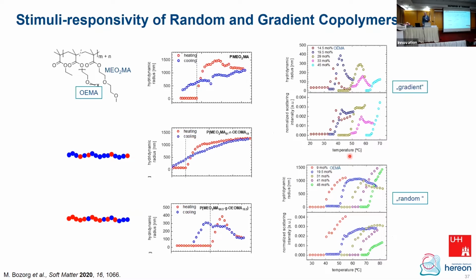Now this gradient copolymer and the random copolymer were investigated in terms of their stimuli responsivity, and showed slightly different behavior, obviously. In the random copolymer, we more or less see one transition as usual. In the gradient copolymer, it's maybe a more gradual change in the transition, because you have less and more soluble parts along the chain. So this is roughly what we expect.